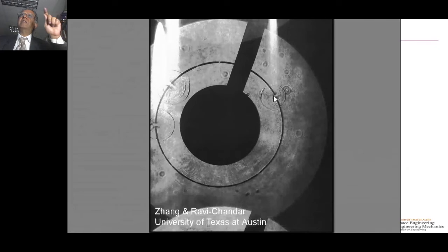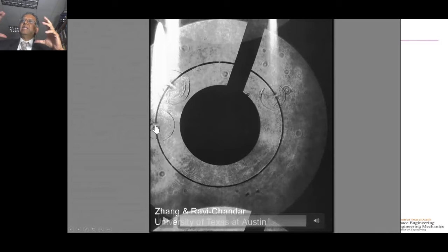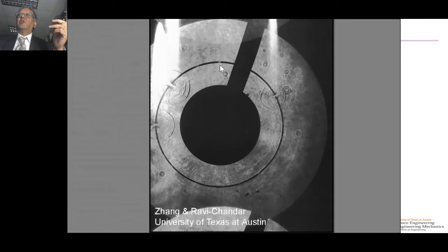You could convincingly prove to within sub-microsecond resolution that this fracture had no way of informing this fracture through any wave, elastic or plastic wave propagation mechanism. So these fractures occur independently of each other. You can also see there are other breaks in here that happen after, because there's no more arcing in these things. The currents have quenched, breaks occur without arc discharge. So you could rank order the order in which the various fractures occurred. And beyond this, the broken fragments simply move as rigid body, and it's not interesting.